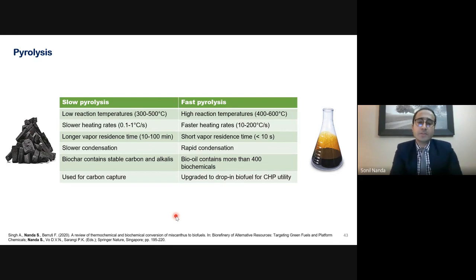In slow pyrolysis, as the name suggests, slow heating rates are involved, ranging from 0.1 to 1 degree Celsius per second, at relatively lower temperatures of 300 to 500 degrees Celsius. And longer vapor residence times are involved, around 10 to 100 minutes.